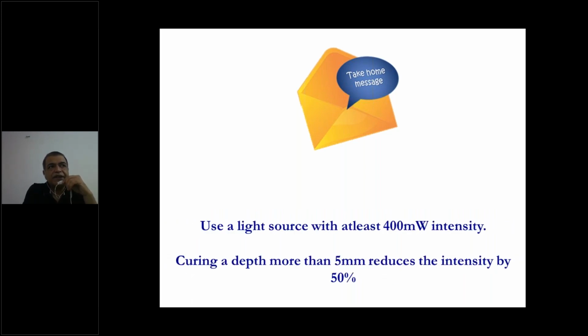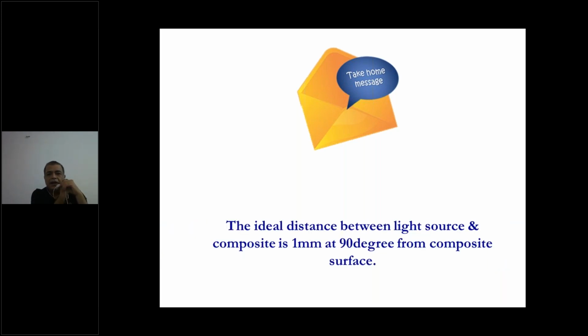Use a light source with sufficient intensity, because with time the composite curing units become old and you will not have sufficient intensity to cure your composites. And when you have a thicker layer of composite, the curing actually reduces. So you may expect less polymerization or less polymer conversion in the deeper layers of composite. That can again lead to failure of the restoration. The ideal distance between the light source and composite is 1 millimeter, at 90 degrees from the composite surface, and if you keep it far, the composite might not cure at all.